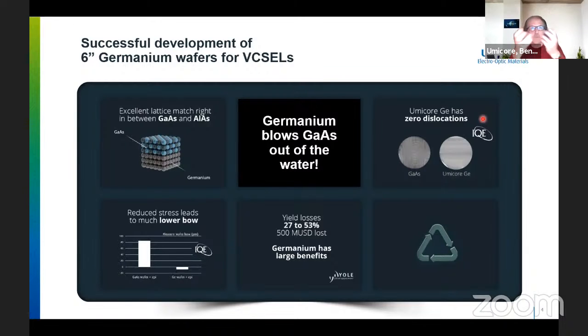And then as a last part, the environmental element is also very important. To have a good thermal evacuation of your heat, you have to grind down your substrates for big arrays because of the heat. And of course, grinding down gallium arsenide is not very environmentally friendly because of arsenic. Germanium can be recycled. Basically, you can eat it. It's very, very safe to use and very easy to recycle. So in the manufacturing of VCSELs, this is also a significant element as environmental things become more and more important. So this is basically the storyline.